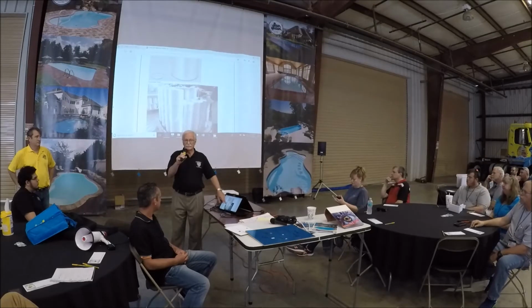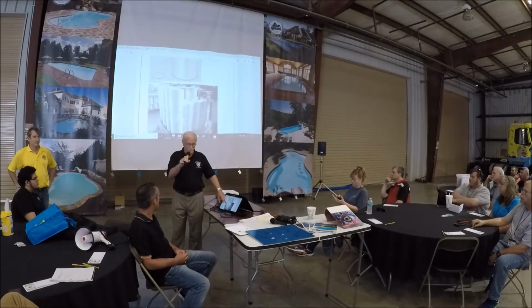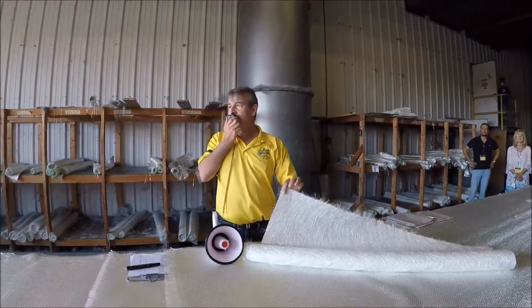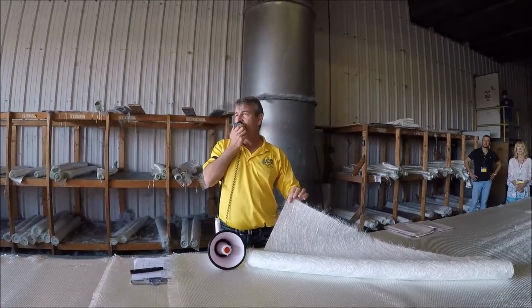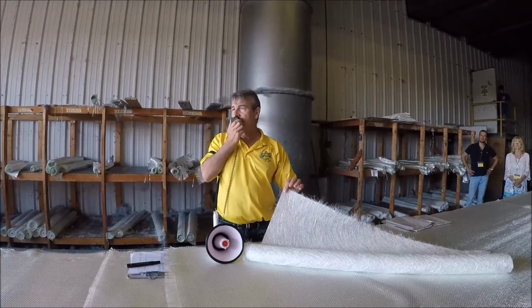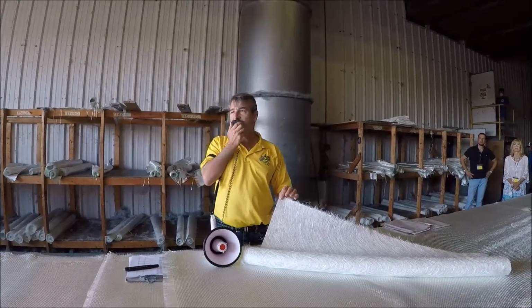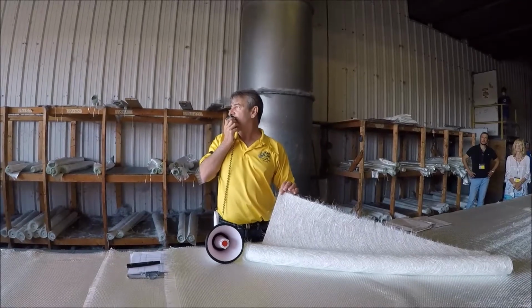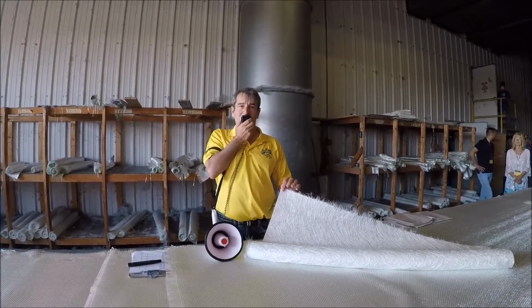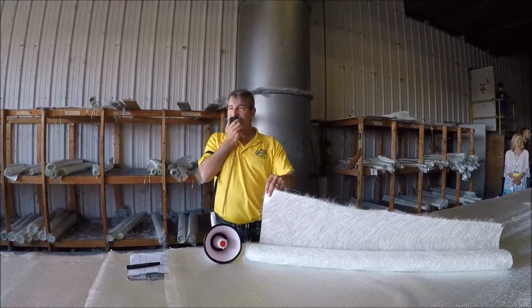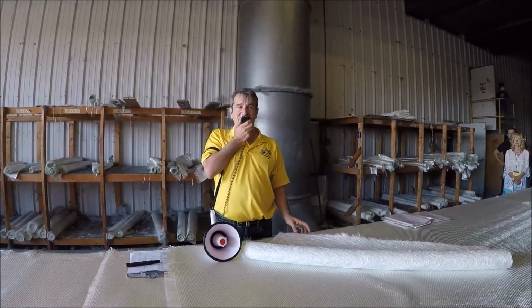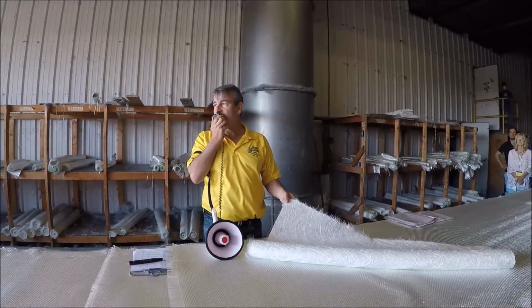you run a creel of roving through a chopper gun. This is called gun roving. It's pretty cheap stuff, and it's the least expensive way to build a fiberglass part if you don't care about structural properties. So this material is put down, and we put down 2 layers of it. It's put down against the gel coat, and it helps support the gel coat material. So while the gel coat is curing out, 1 layer of this is rolled into it, and that then gives structural support to the gel coat.